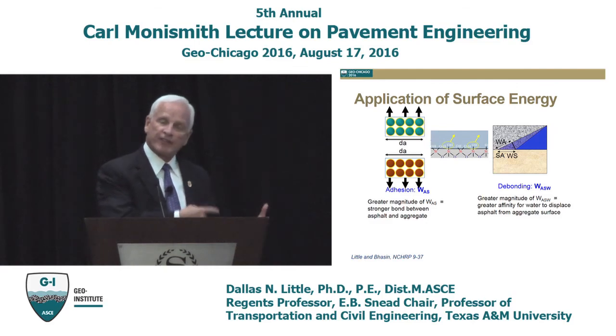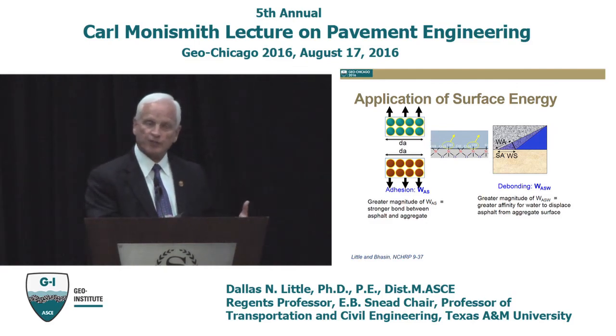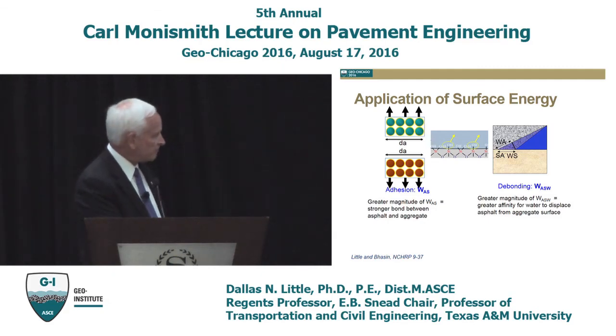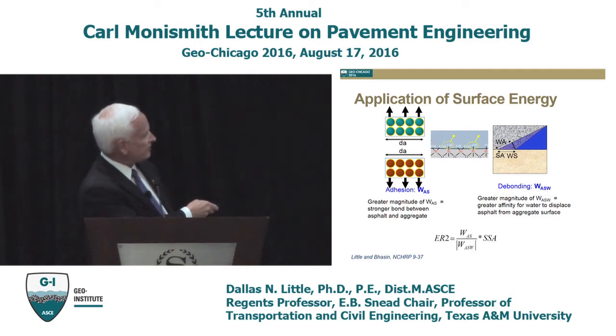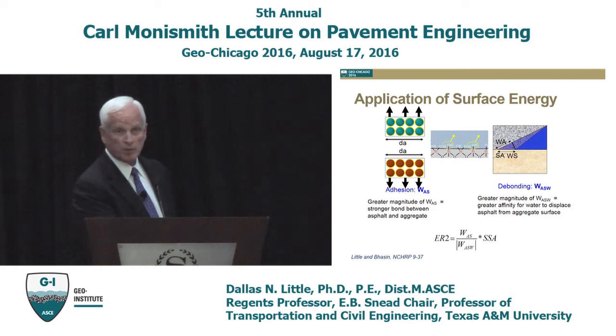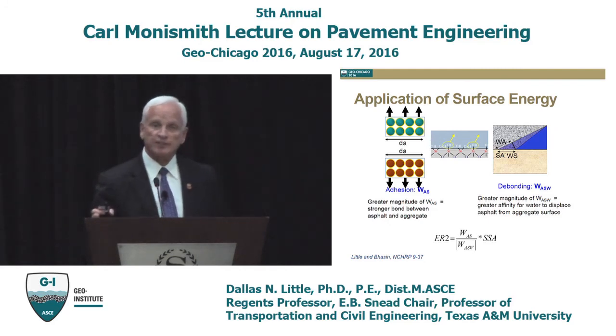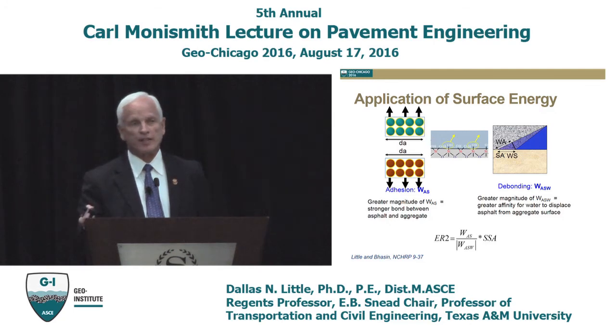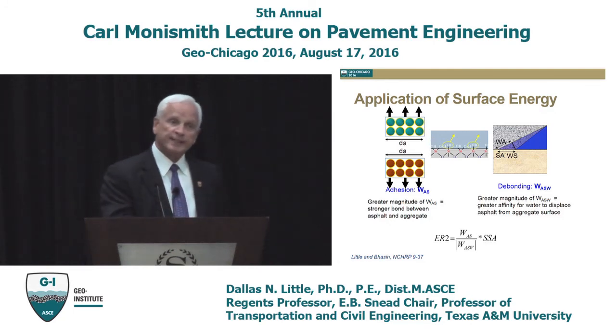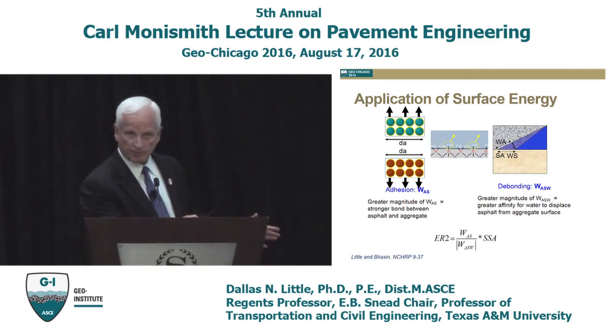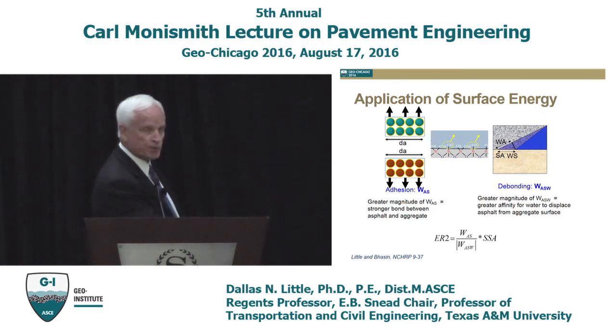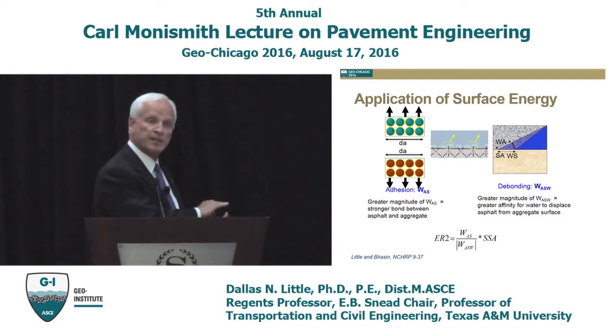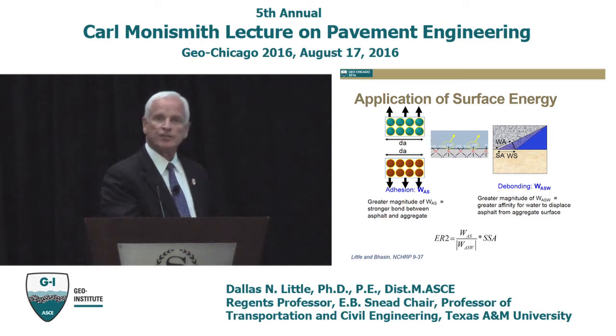The magnitude of the negative value defines how strongly water wants to replace asphalt at that interface. So if we were to take a ratio of the bond strength in the numerator between the asphalt and the stone, and the absolute value, because this term is almost always negative, of the work of adhesion of the asphalt and the stone in the presence of water, that energy ratio is something that we would want to be large. So we can measure the surface energy of the aggregate, the surface energy of the asphalt. We can measure them in the presence of water, and we can come up with this energy ratio that we want to be large. Because we want the dry bond strength to be great, we want the absolute value of Gibbs free energy, which is going to be negative, to be as small as possible, to make our system as good as possible.